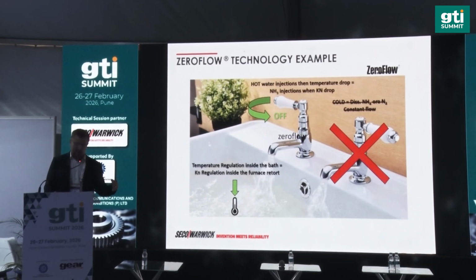We create the high temperature, which means high potential, in the first stage of the nitriding. It's usual, as all technologies on the market use the same way, but for the second stage we just close the tap, that's why we call it ZeroFlow, and wait for the internal dissociation. Based on our technology, we are able to achieve any nitriding layer compounds as we want, same as traditional technology. The difference is that we use much less ammonia to do this. It means lower consumption, lower cost, and also lower emission of post-process gases.